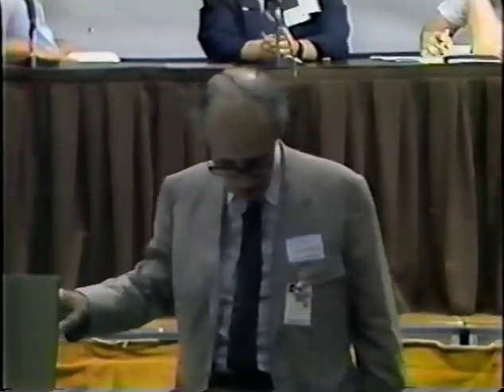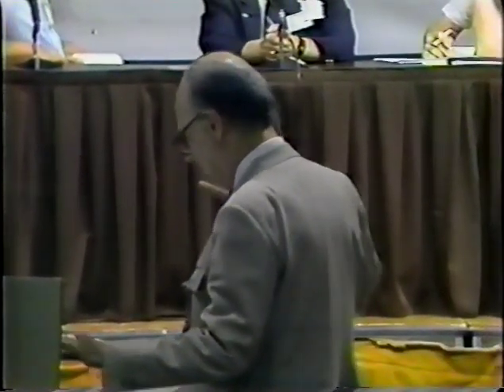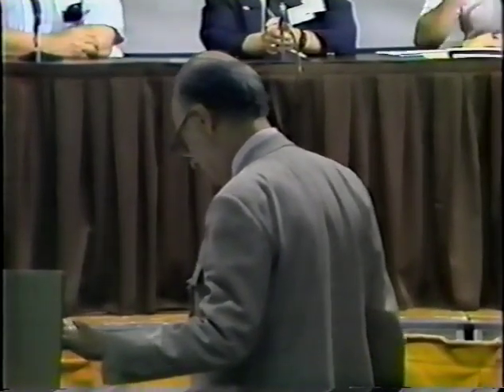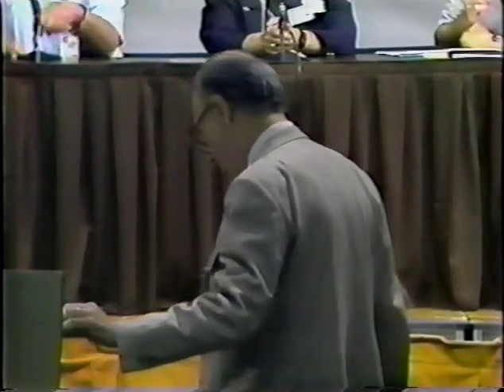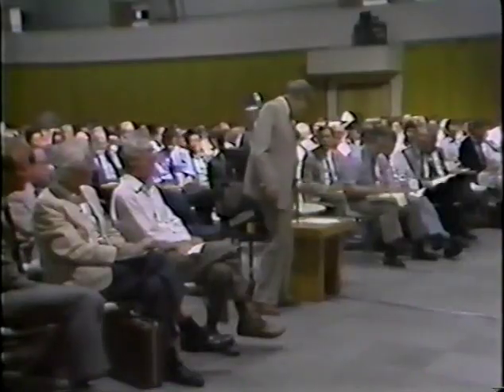And the relationship, which, by the way, I didn't have a book for, I remembered this roughly, I hope the figures aren't too wrong, is something like this: when the fugacity goes up to something like 10 to the 12, the pressure is way down at 10 to the 4. These are all atmospheres, 10 to the 4, 10 to the 5. And that's not an unreasonable pressure inside a metal. You get yielding and spalling at 10 to the 4, 10 to the 5. But it would be possible, perhaps, to agree with fugacities of 10 to the 12 and pressures of 10 to the 4.